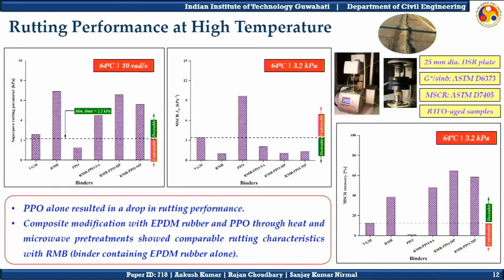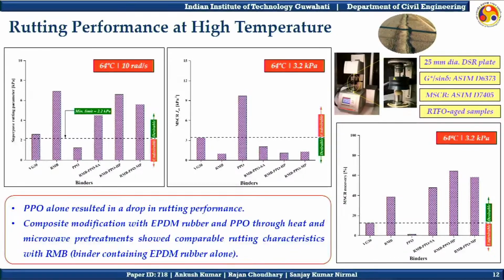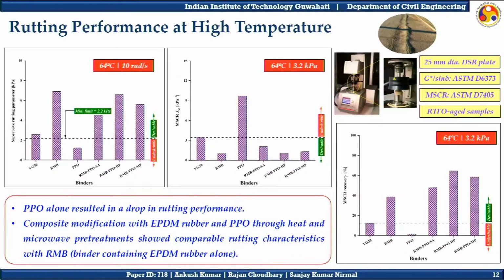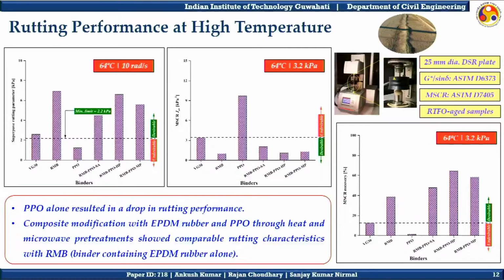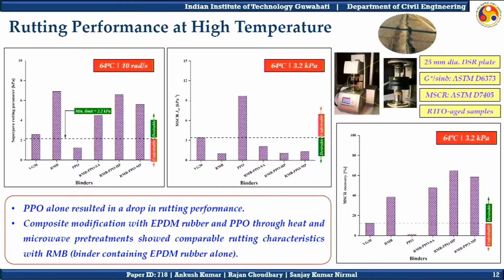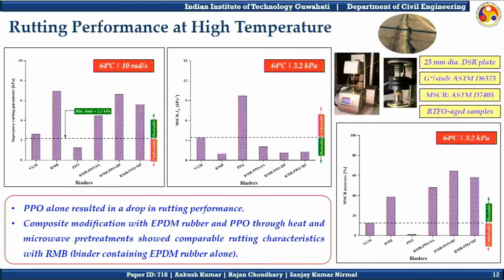While in MSCR recovery, the recovery for composite rubberized binders were significantly higher, and the recovery of the composite rubberized binder after heat pretreatment was about 250% higher than the base asphalt binder. So this indicates that the pre-swelling of rubber with PPO under pretreatment, these pre-swelled rubbers act like flexible particulates in the asphalt matrix, and those particulates are able to deform under loading, and they are able to reform very well when the loading is removed.